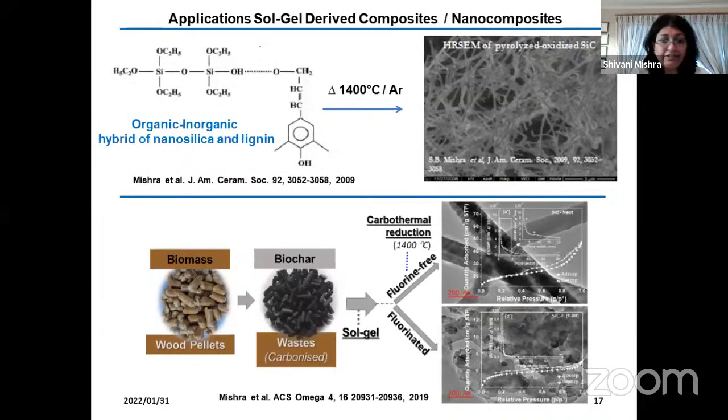But honestly, we did this reaction, and there is a possibility that while doing the reaction, there is a byproduct, hydrogen fluoride, which at the beginning of the reaction, when we did the carbothermal reaction, reacted with the silica and ate up my silica. So silica was not at all available for further reaction and we got everything collapsed here. However, we could see some nanofibers here and there in this network, those small lines here, still trying to exist in the system.